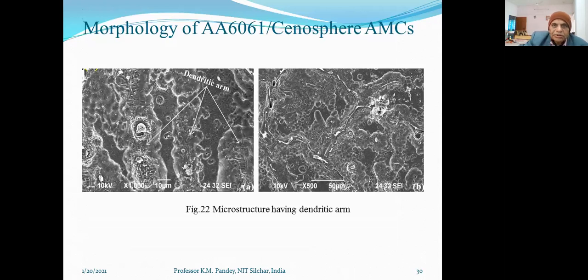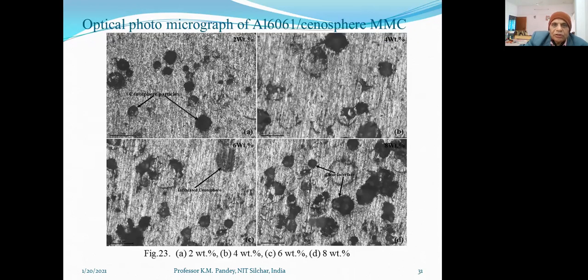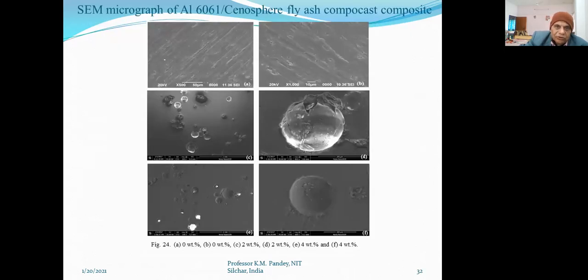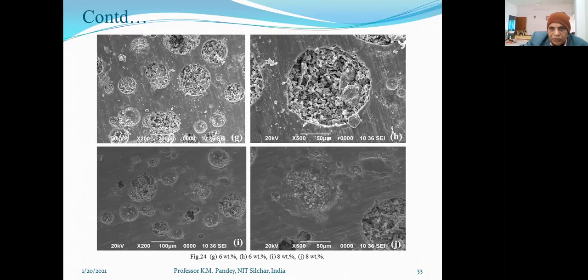Then this is the morphology of AL6061 cenosphere AMC, that is microstructure having dendritic arms. So this is the figure. Then next, this is the optical photomicroscope micrograph of AL6061 cenosphere AMC. Here we have used four variations: 2% by weight is added, then 4% by weight, then 6% by weight, then 8% by weight. So four variations we have taken. Then this is the SEM micrograph of AL6061 fly ash composite. This is also self-explanatory. Then this is another figure.